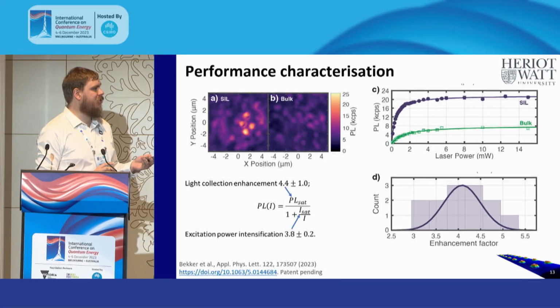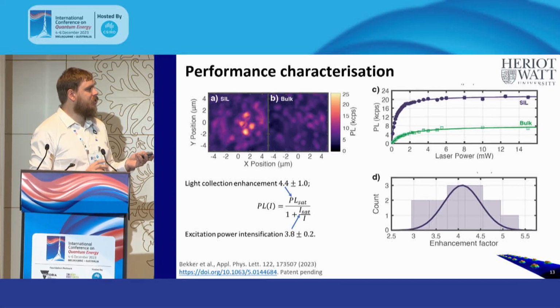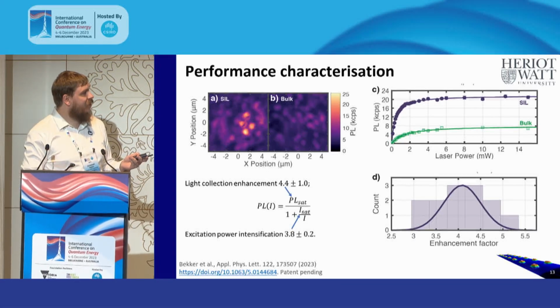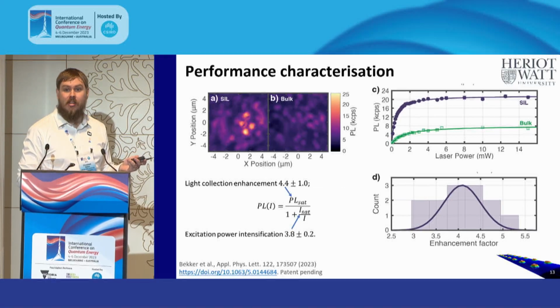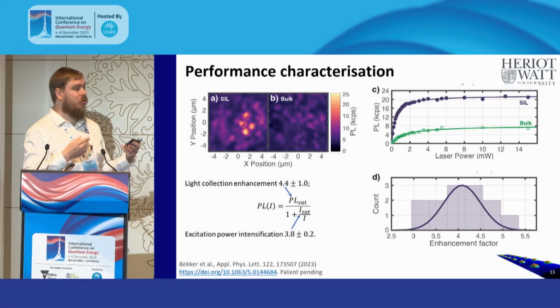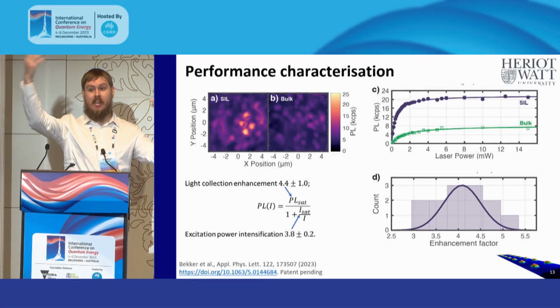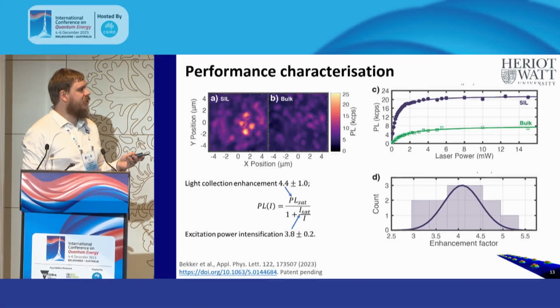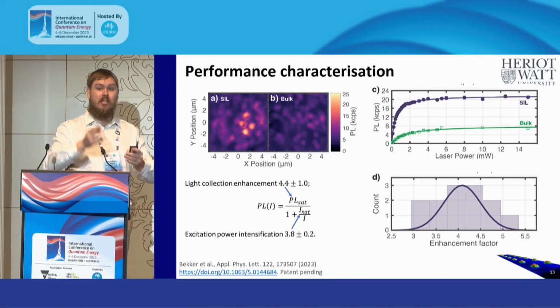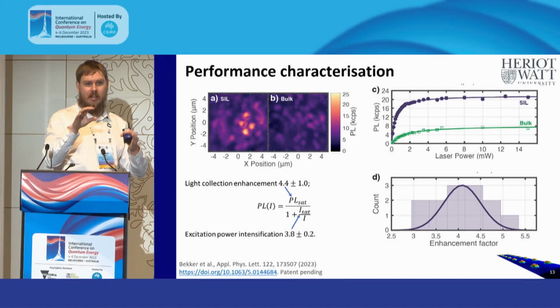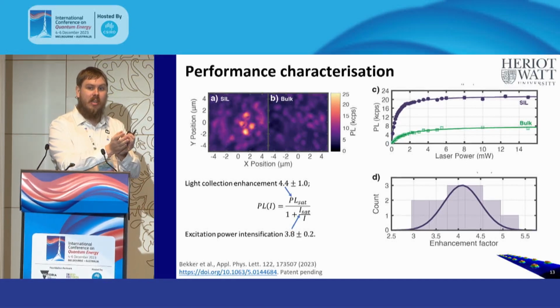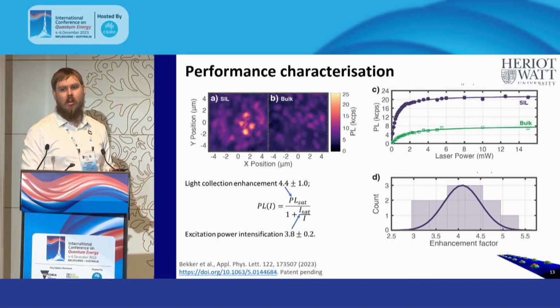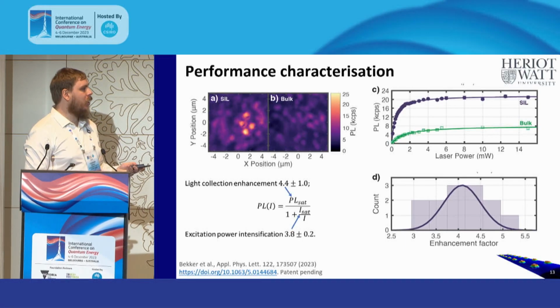So this curve here follows this equation, and there are two elements of enhancement. One is the fact that our saturated brightness is higher because we now enhance the amount of light that can leave the crystal. The other element is that because we are shining our light through a lens, we make our excitation spot on the emitter smaller. So we also start saturating earlier. And that's this power intensification here.